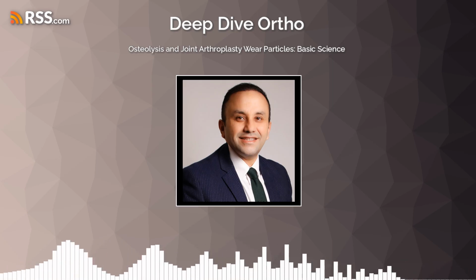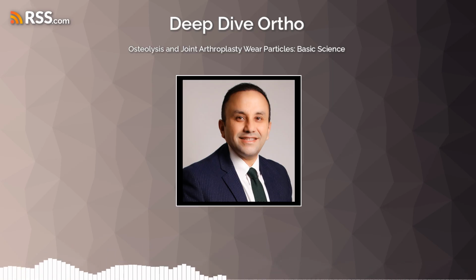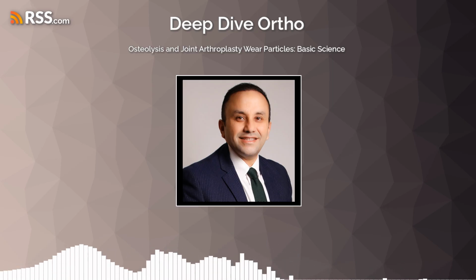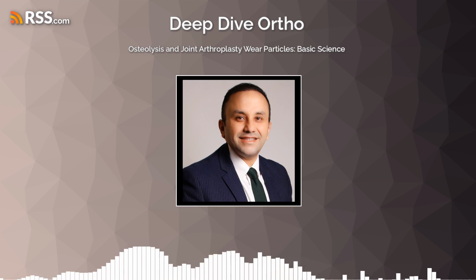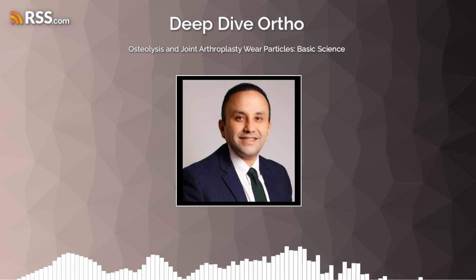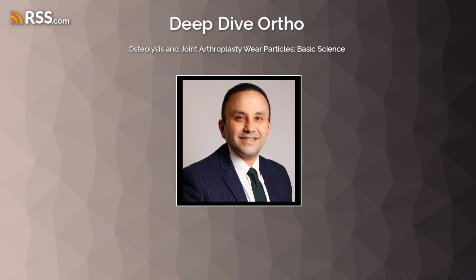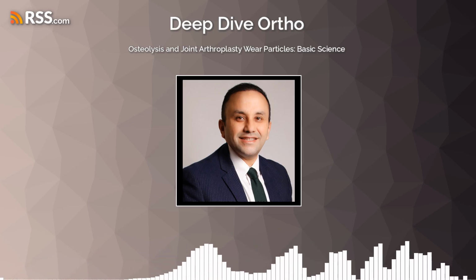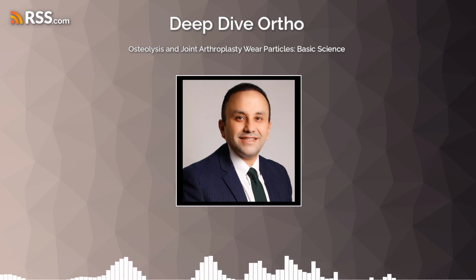However, it's important to acknowledge a trade-off. Highly cross-linked UHMWPE can have slightly reduced mechanical properties. Compared to conventional non-highly cross-linked UHMWPE, it could potentially be more susceptible to other forms of failure, like fatigue cracking or delamination in certain circumstances, though its wear resistance remains superior. Okay, so it's not a perfect solution, but much better on the wear front.